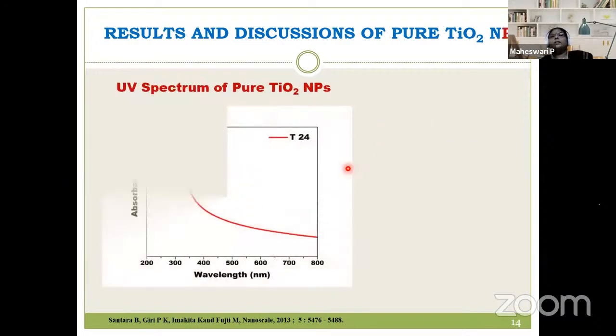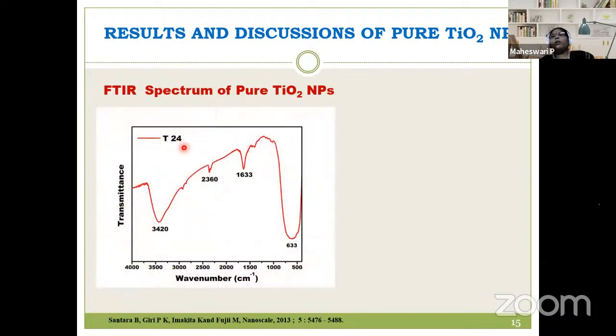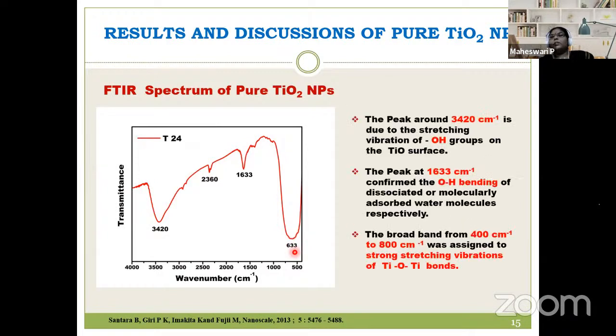Then we went for the UV analysis. From the UV analysis, we were able to see the maximum absorbance of our synthesized particle, around 264 nanometers. Now, in the case of the FTIR spectra, from the data available here, this is normally known as the fingerprint region of IR spectroscopy. Under that, you can see 633, which is a very important, strong stretching vibration of the Ti-O bonds.